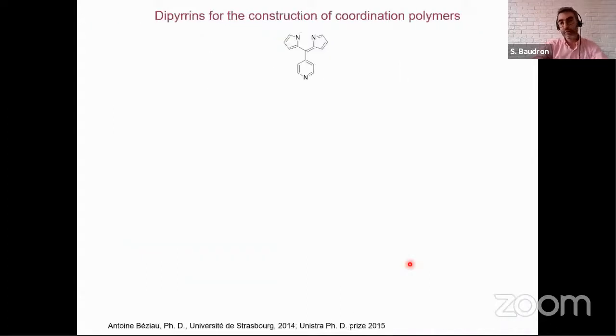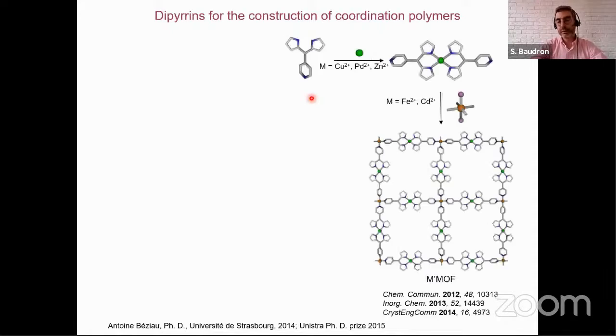In our case, we have also investigated this type of construction of coordination polymers with a whole variety of ligands, and I'll come back to that later. But again, we can take as an example the dipyrrin-pyridine derivative. We have shown that upon reaction with copper-2, palladium-2, or zinc-2, we can form a metal complex that is an analog of 4,4'-bipyridine, with 2 pyridines at the periphery that can be assembled with iron-2 or cadmium-2 units to form this type of heterometallic 2-dimensional coordination polymer.